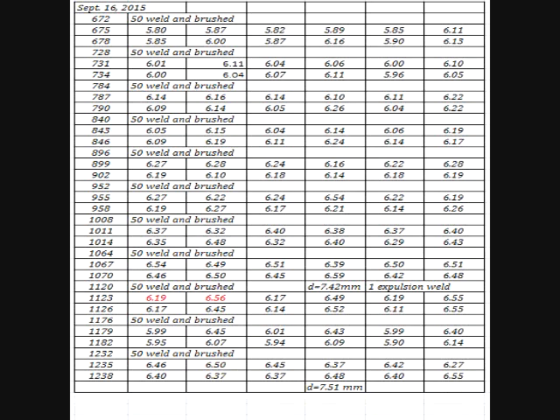At the end of the whole experiment, we totally accumulated 1,238 welds, and the diameter of the weld cap increased by 1 millimeter. And if you divide 1 millimeter by 1,238 welds, each weld basically increased the diameter of the weld cap less than 1 micrometer.